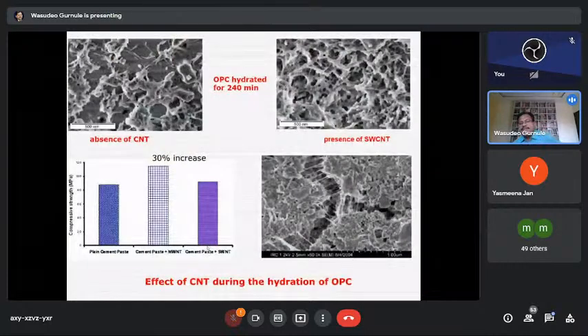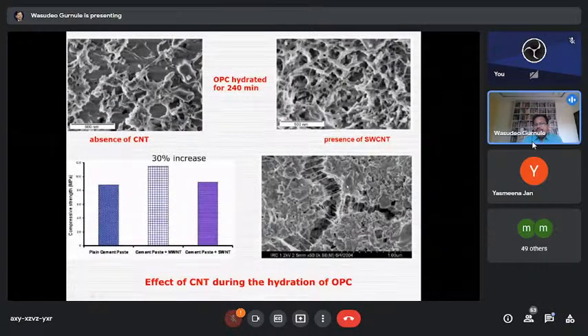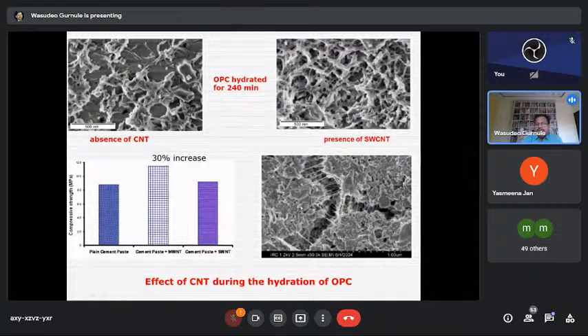And it is also observed that the addition of nano size CNTs in cement, also in Portland cement, gives an increase of 30% in the efficiency of the cement. Here the graph shows this picture. Now this morphology is shown in the absence of CNT. What is the nature? See now here, sticky material. And after that, the presence of single walled: now it is very compact, so gaps are now less. And when we use multi-walled, see the nature, very sticky, very close and very strong bonding. So three different figures are being shown.